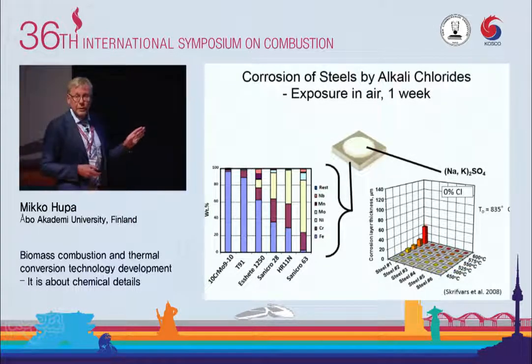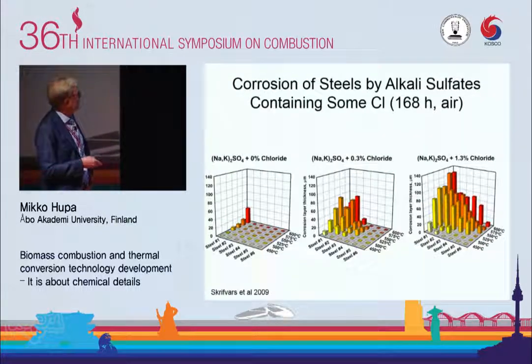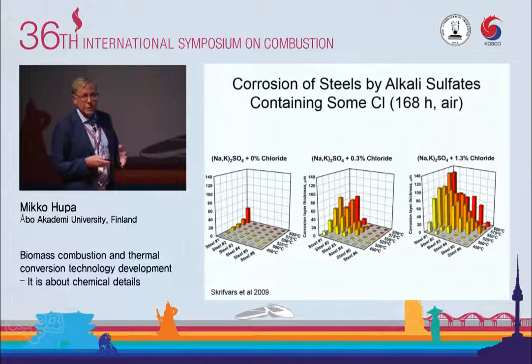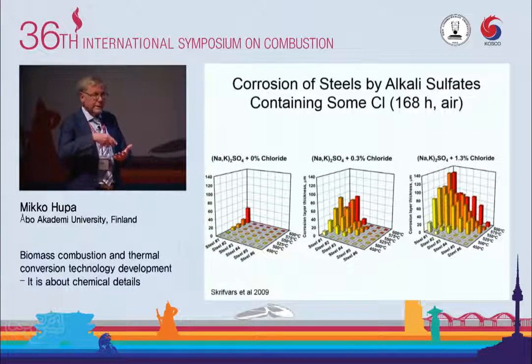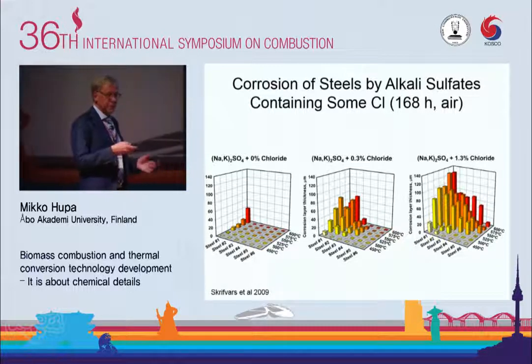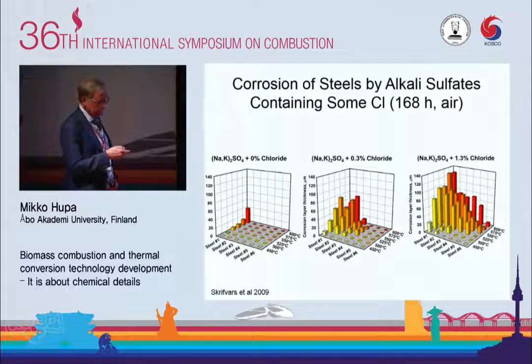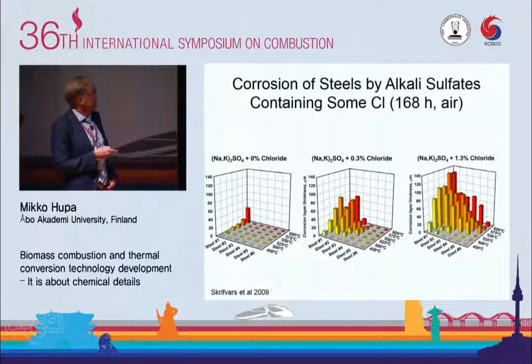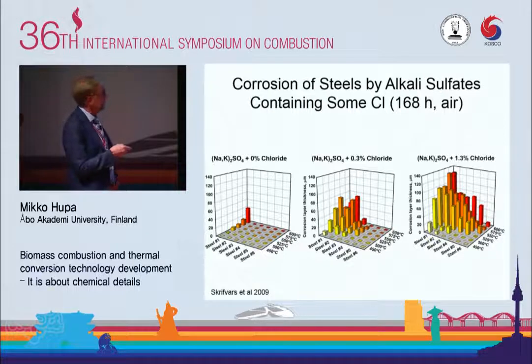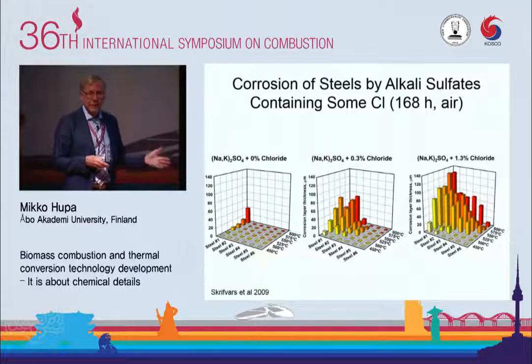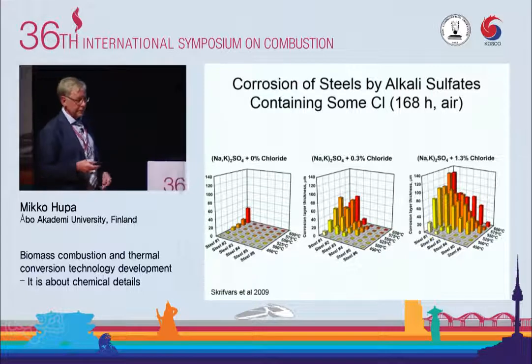However, when we start mixing chlorides, small amounts of chlorides into this system, this is the one I showed to you. We put 0.3% chloride. We did it by putting sodium chloride or potassium chloride into this sulfate, melted it in advance, and cooled it and crushed it. So it was very homogeneously mixed, the chloride. And you see that now these materials already start showing heavy corrosion. These are high numbers. These are micrometers per week. And this is already visible by eye on that short time. And when we have 1.3% chloride, even the most expensive materials started showing clear corrosion at 525, explaining how this is really the obstacle to going to higher steam temperatures.